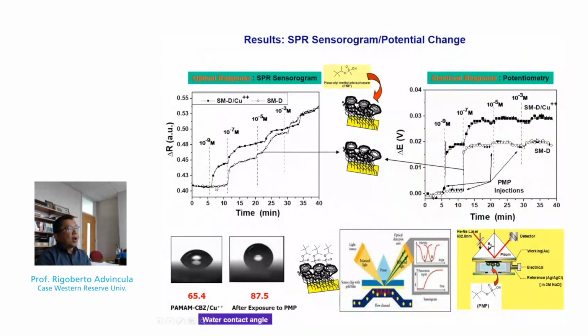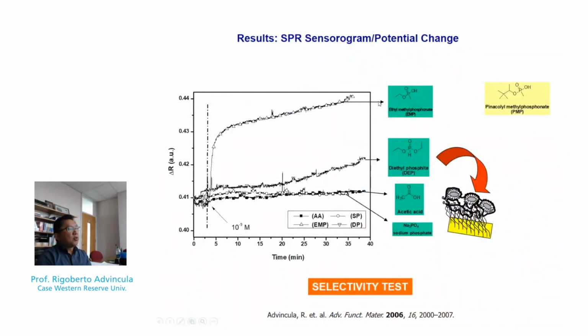So as a sensor, one can monitor the response based on reflectivity or potential. That means that as we introduce increasing concentrations of the PMP analog or sarin analog, we can see an increase in reflectivity, indicating a linearity of detection. On the other hand, this was also confirmed by potentiometry. But what's interesting is this detection goes all the way to nanomolar limits. In fact, just to demonstrate what we call selectivity, this sensor was sensitive for PMP, EMP, but when we introduced DEP, acetic acid, sodium phosphate, the response was low. And we attributed this to the very good complexation behavior of PMP and EMP against the dendrimers.